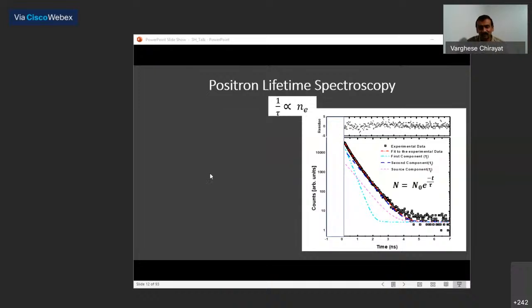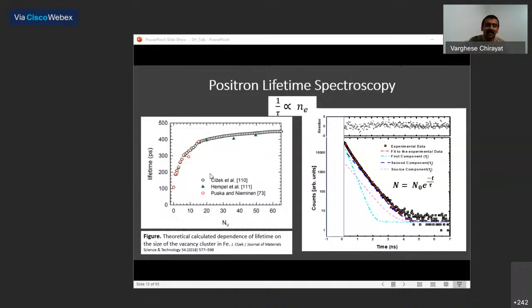Okay, so for example, I have given here the lifetime of a positron as a function of the size of the vacancy. Okay, so 0 means it is a defect-free material. So if the positron is inside a defect-free material, and the material here is a well annealed, well heated iron sample, and there are no defects inside the material, you will get somewhere close to 110 picoseconds. 110 times 10 raised to minus 12 seconds. Okay, that is 110 picoseconds.